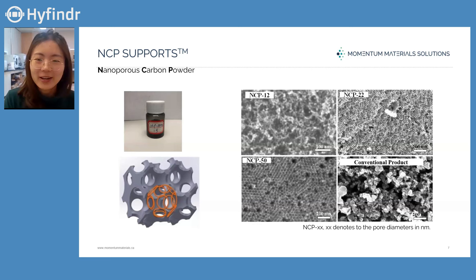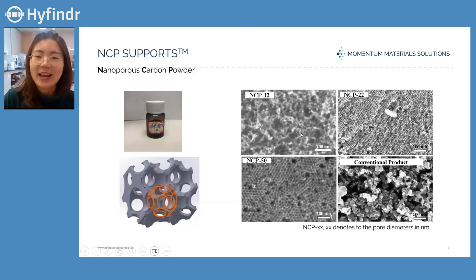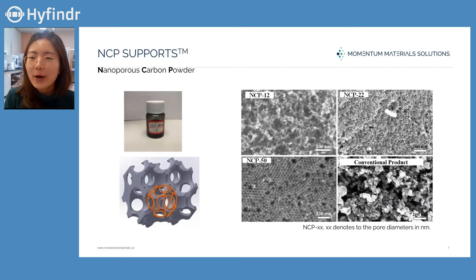Can you tell us more about what you've done? Here are the actual morphology images of our nanoporous carbon materials. These images were collected by SEM — scanning electron microscope. We are currently able to make nanoporous carbon powders with different pore sizes ranging from 10 nanometers up to 100 nanometers. You can see that we are really able to control the pore size and make a very organized pore structure.